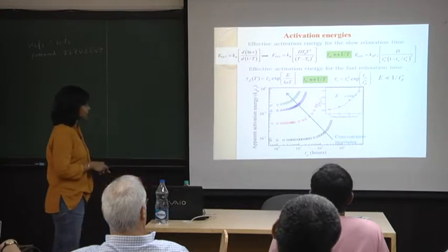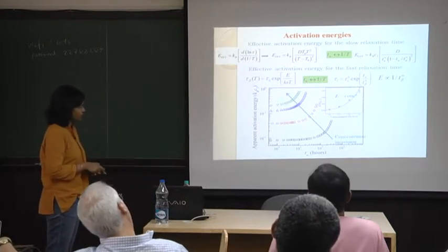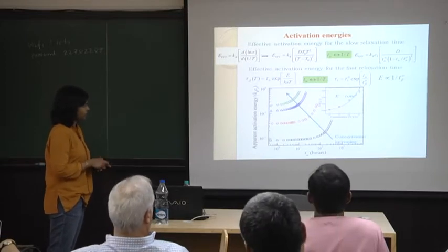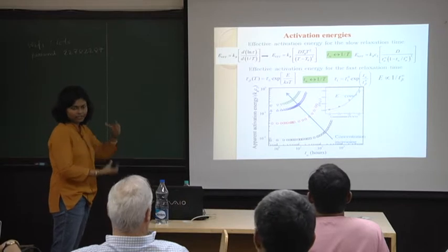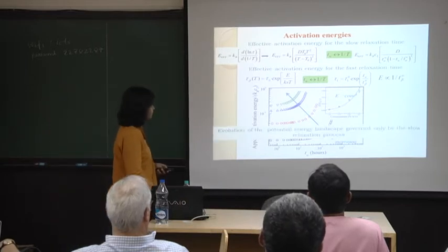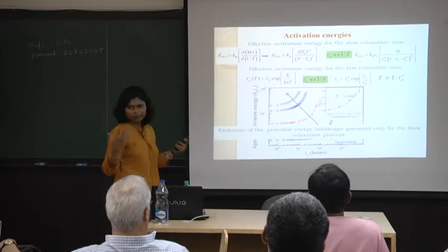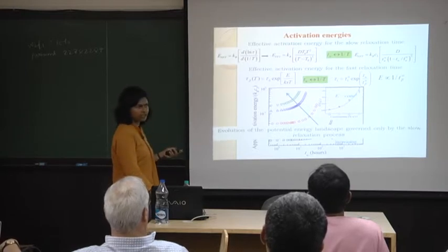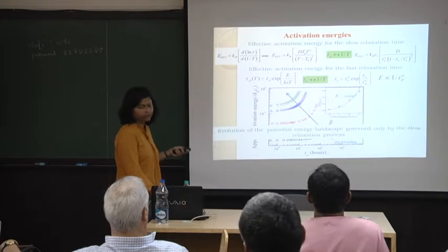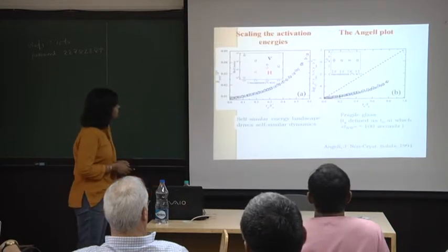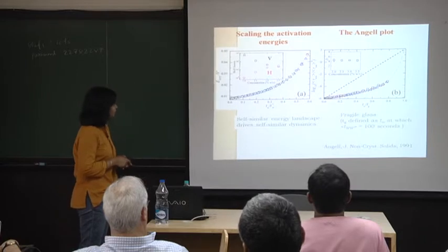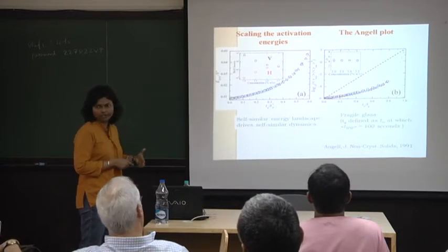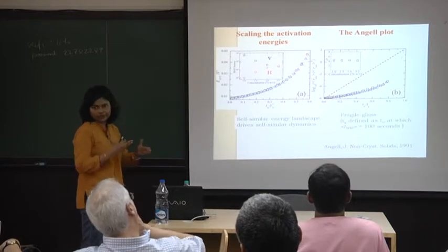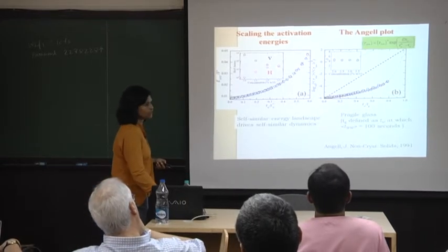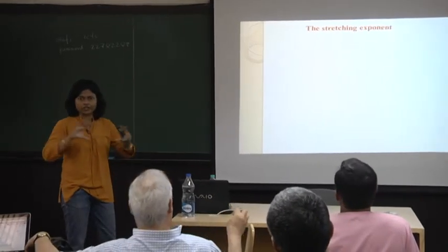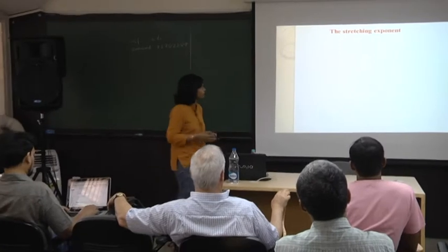This is the apparent activation energy versus the age for the slow relaxation times, and this is how it goes as concentration increases. You can see that the wells are getting deeper and deeper here. The point I'm trying to make is that the evolution of the potential energy landscape in this case is governed only by the slow relaxation process. The activation energies we've calculated also superpose very nicely if you scale your data, which shows that you have a self-similar evolution of the potential energy landscape as the particle ages.